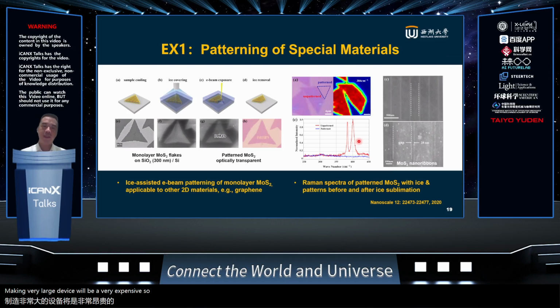But they do have tons of advantages, including, for example, and this is the first example, a publication two years ago. We can pattern very special materials, including 2D materials. And we have actually tried several materials, including monolayer MoS2. And this material is quite difficult to process by nanofabrication.